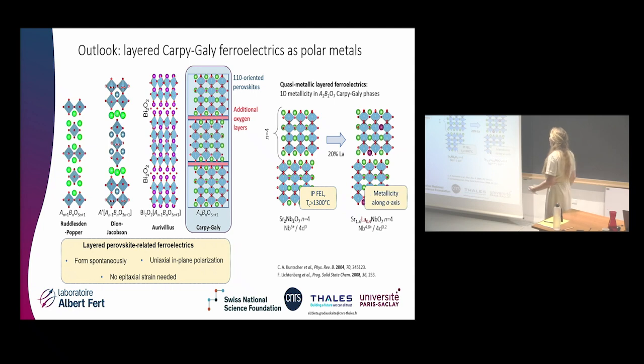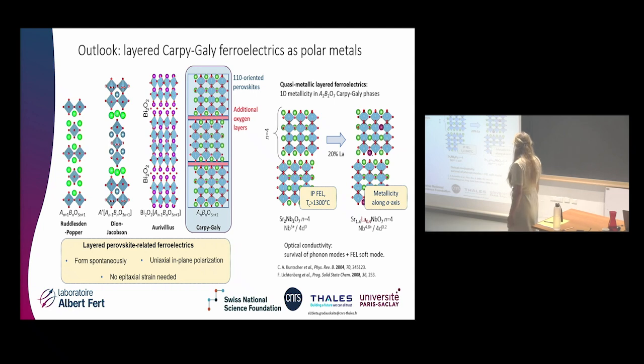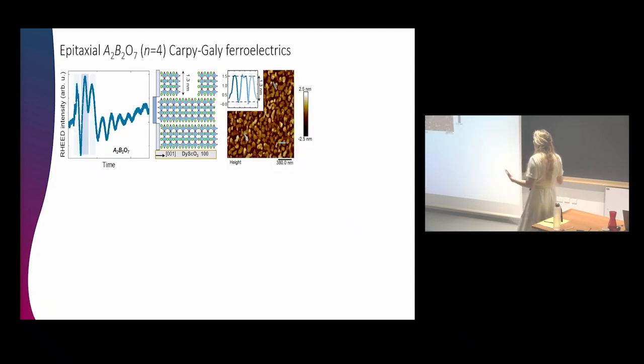So far, it's only been shown in bulk, but as you can imagine, you heard already the talk from Manu this morning that polar metallicity is something very interesting and very new, and we were definitely intrigued by the concept of somehow having this ferroelectricity and metallicity coexisting, especially that in bulk it was shown that while it's conducting, the phonon modes and ferroelectric soft modes seem to be surviving, so there seems to be some coexistence, and that was the original motivation.